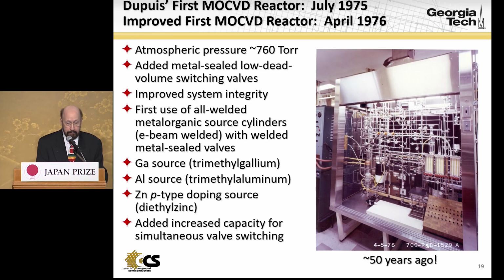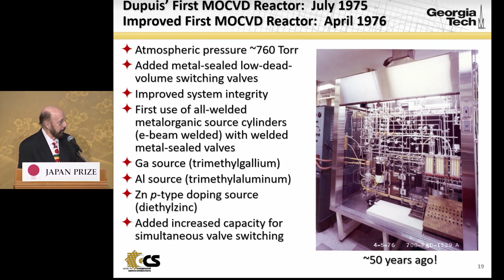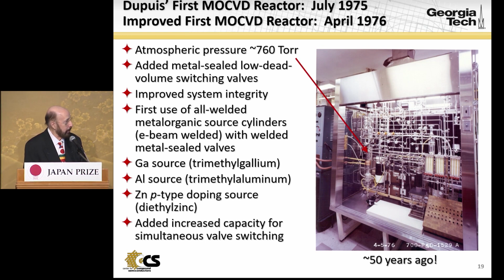This is a photograph of one of my early reactors, not the very first one I built, but one from approximately April 1976 when this photograph was taken. It's an atmospheric pressure reactor, small quartz vertical chamber, 2-inch diameter susceptor. It has some innovations, including metal seal low dead volume switching valves to switch the precursors in and out of the reactor stream, improved system integrity, including the use of all welded metal sealed bubblers for the metal organic sources like trimethyl gallium and trimethyl aluminum, which are shown here.